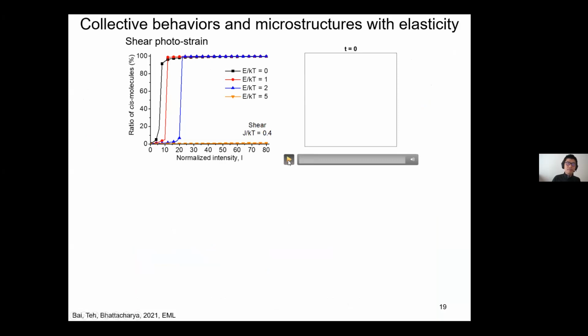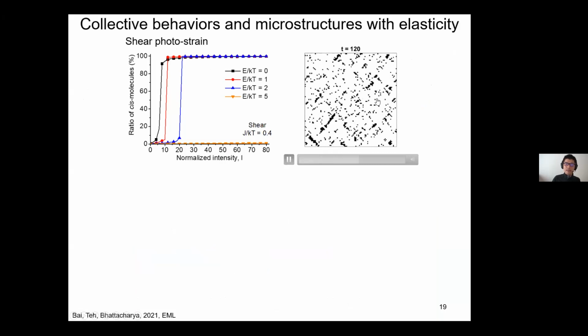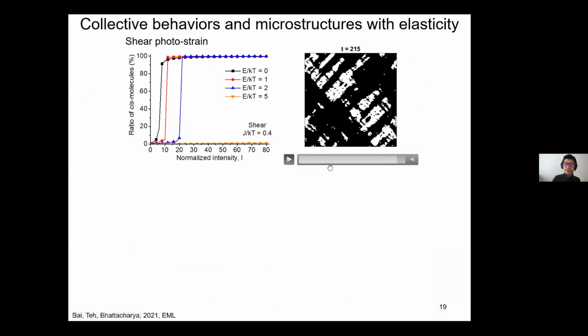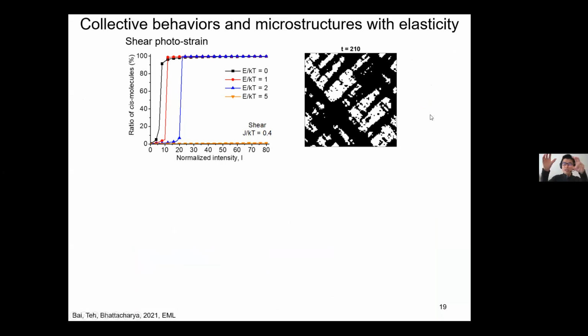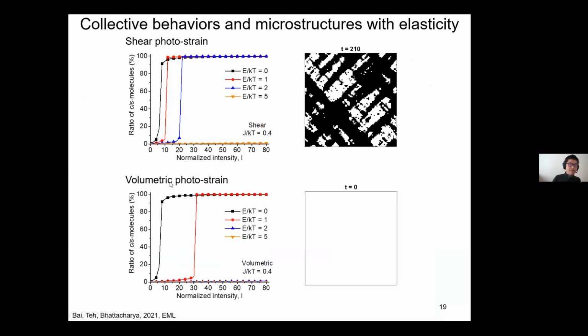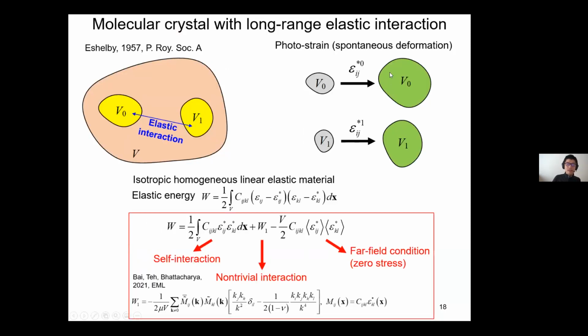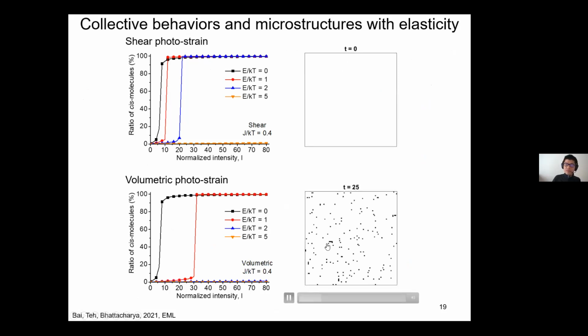Okay. Now, let's still look at this kinetics. Initially, again, I have some random domains, but then slowly you see that I have some very interesting microstructure evolving, and it's called a twin structure, or you can call it the stripe structure, right? To record this photostationary or equilibrium state, again, you see you have a very nice first order phase transition. However, in volumetric strain, which means in this previous page, this deformation now is a volumetric expansion or shrinkage, okay? It's very different.